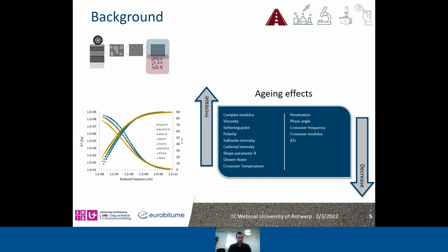For example, on the left you can see how aging affects the rheological master curves. There are obvious changes with aging, with standardized simulations like rolling thin film oven testing and the pressurized aging vessel, that increase the complex modulus and decrease the phase angle. These are known changes because of aging in rheology, but there are also other effects of aging, extracted from master curves, rheological parameters, but also in different chemical variables, for example, changes in solubility or polarity-based fractions of bitumen, widely known as SARA fractions.